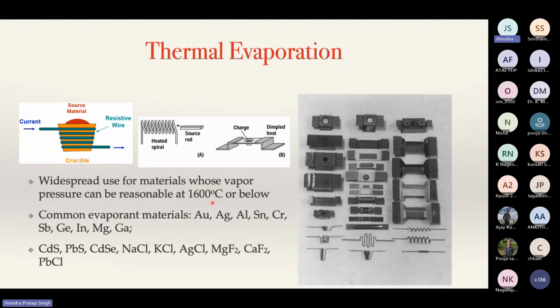That's why you see in the chambers we normally use some kind of a cold jacket to cool down the chamber, so that the chamber wall should not start dissolving. If they start dissolving, then your film will get contaminated also. So that is one of the drawbacks of thermal evaporation, because we cannot go to very high temperature. And the common materials we use are gold and silver. Mostly these materials are used for the metallization part, making ohmic contacts or Schottky contacts on the devices.